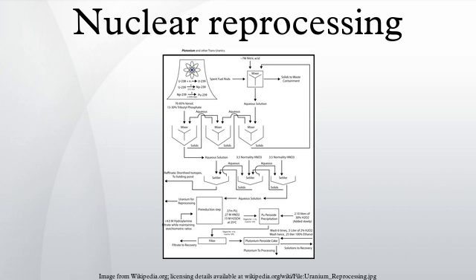Voloxidation. Voloxidation involves heating oxide fuel with oxygen, sometimes with alternating oxidation and reduction, or alternating oxidation by ozone to uranium trioxide with decomposition by heating back to triuranium octoxide. A major purpose is to capture tritium as tritiated water vapor before further processing where it would be difficult to retain the tritium. Other volatile elements leave the fuel and must be recovered, especially iodine, technetium, and carbon-14. Voloxidation also breaks up the fuel or increases its surface area to enhance penetration of reagents in following reprocessing steps.